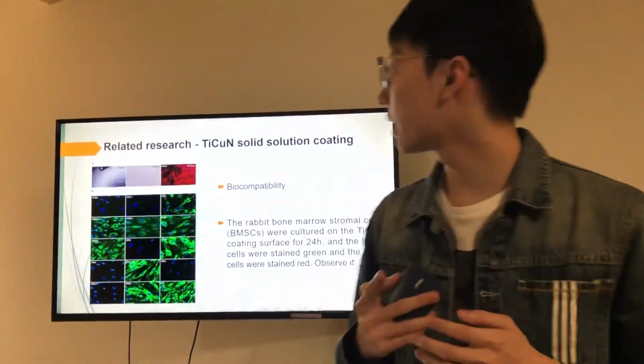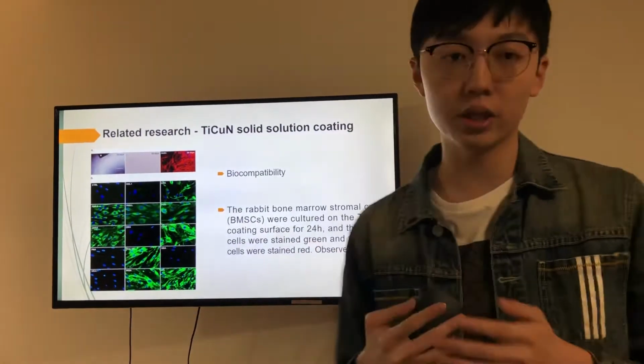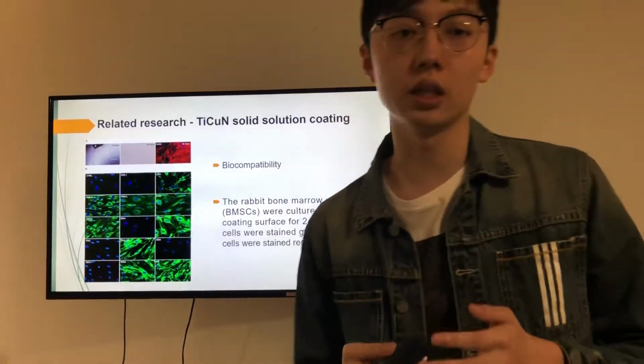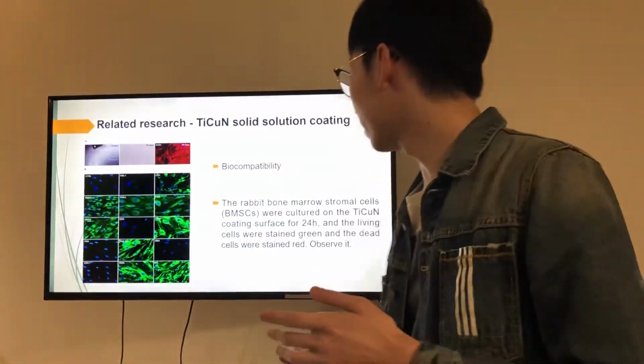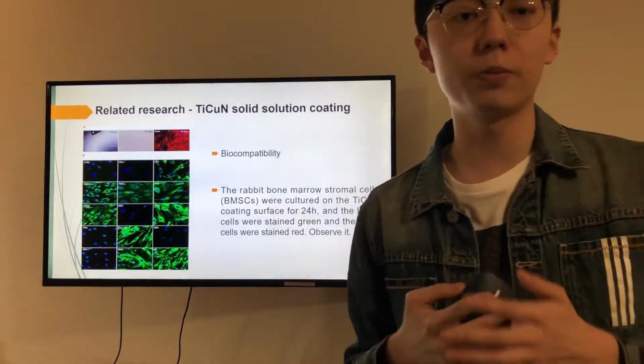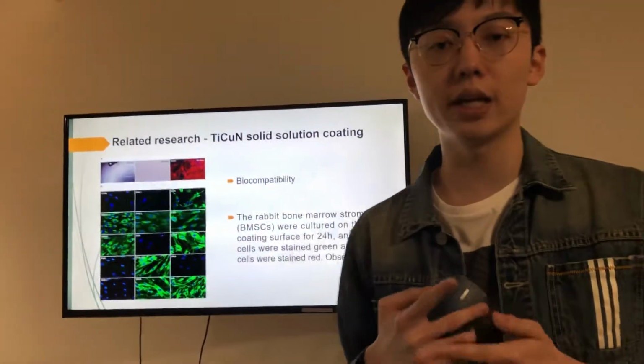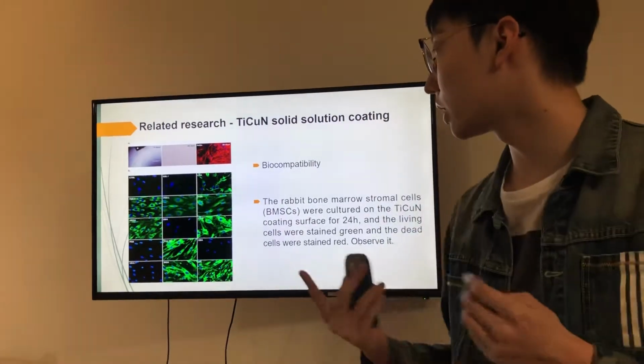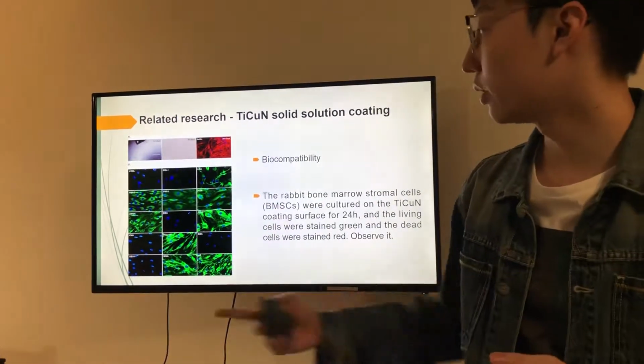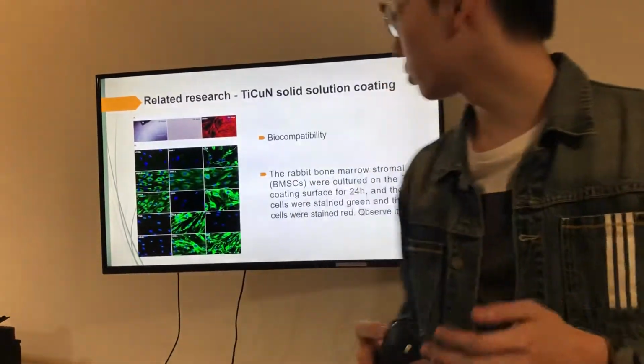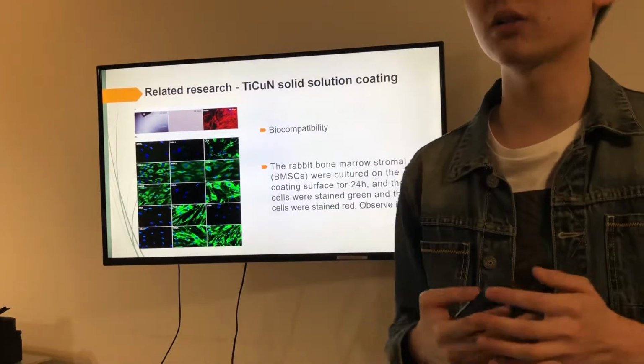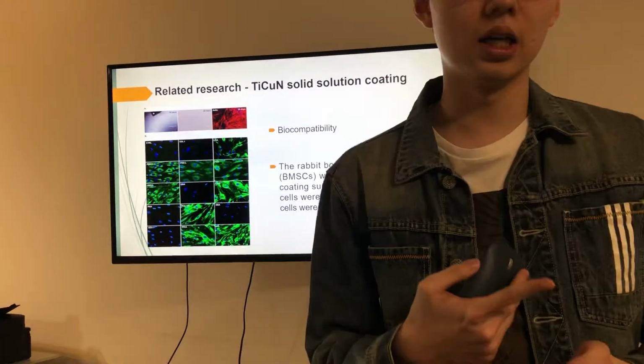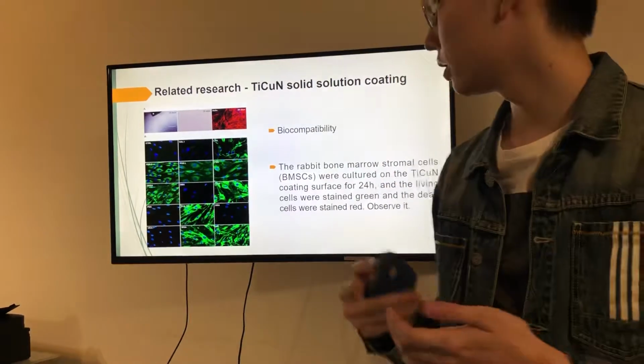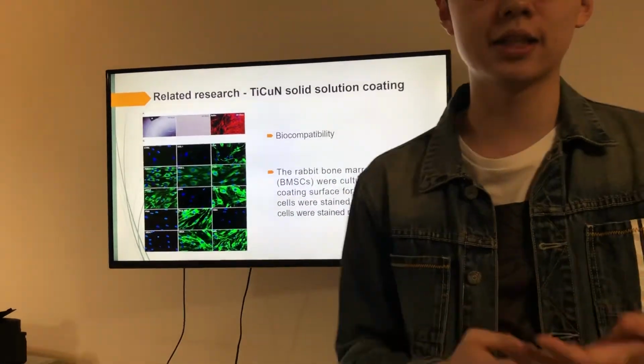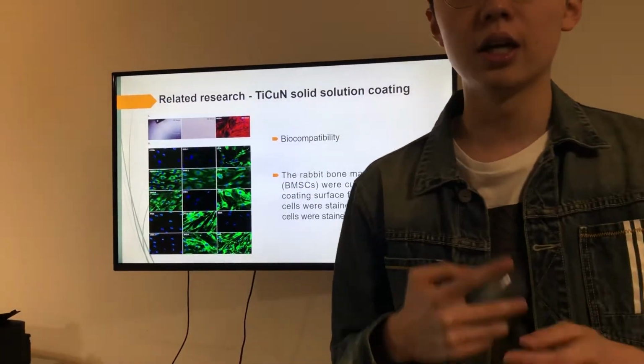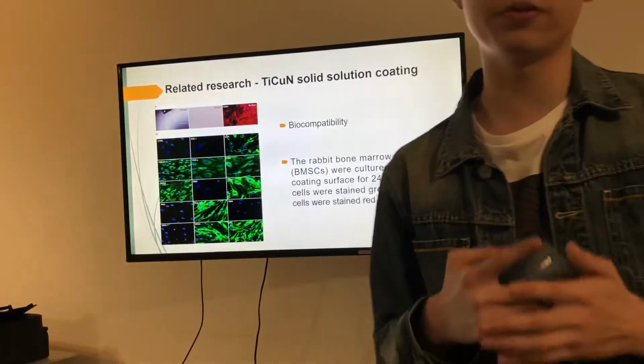The titanium copper nitrogen solid solution coating was researched by Zhang et al. They observed the rabbit bone marrow stromal cells, the BMSCs, on the titanium copper nitrogen coating surface by staining the living cells green and the dead cells red after 24 hours of culture. These are the dying cells, and these are living cells. You can clearly see the shape of these cells. They observed them by SEM and microscope and found the survival rate of the living cells. The results show that the titanium copper nitrogen solid solution coating is a kind of medical material with good biocompatibility.